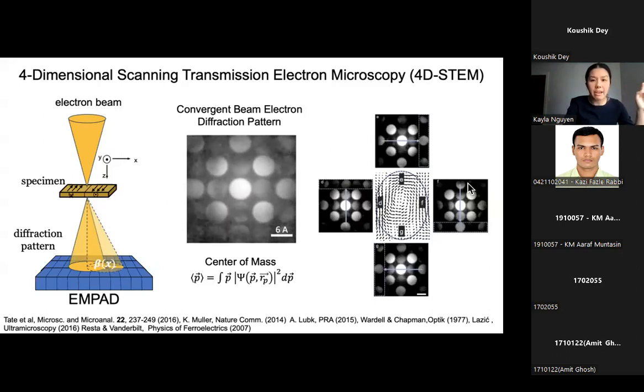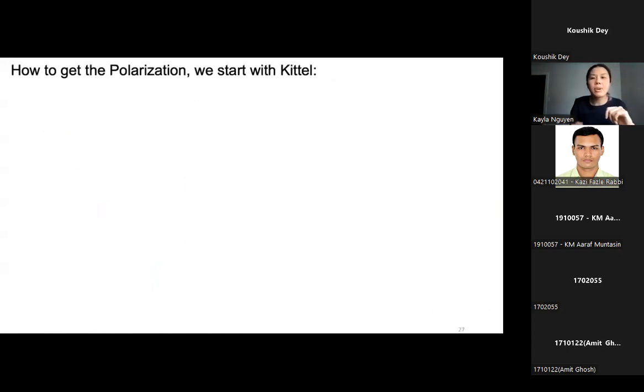The right part F goes from top to bottom. The G part here goes from right to left, and the D part goes from bottom to top. So if we track the change in our non-overlapping diffraction disk, we can also map out the polarization vortex this way. And so how do we get back information related to polarization vortices?